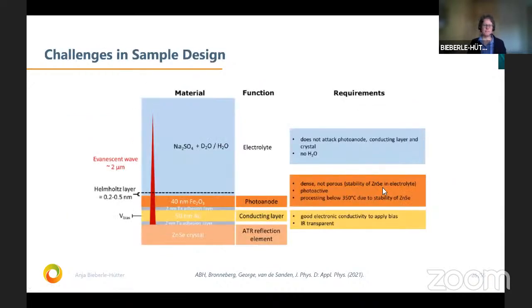The challenge there is the sample design, because when you have this infrared beam, you have to have an infrared transparent conducting layer, for example, on top of it. You have to deposit the iron oxide on top of all these. The zinc selenide crystal should not see too high temperatures. So you understand from this that on the material side, the processing is not so easy, and this actually also delayed us in finding a good low temperature processing of iron oxide.